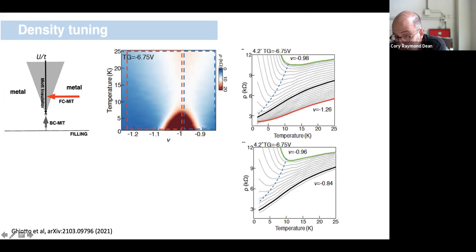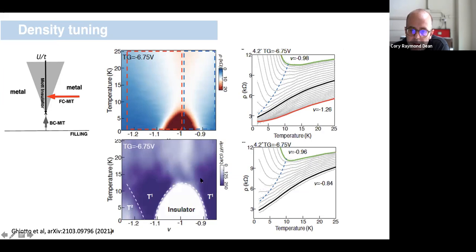Okay, so if we just take the temperature derivative of all these curves, basically this plot, and we replot that, then what we can identify and label is basically the entire phase diagram as we transition from the insulator through this kind of T-linear regime, as a function of temperature and filling now, and then to something that looks more like a Fermi liquid regime, T-squared dependence. Okay, so let's look at this in slightly more detail.